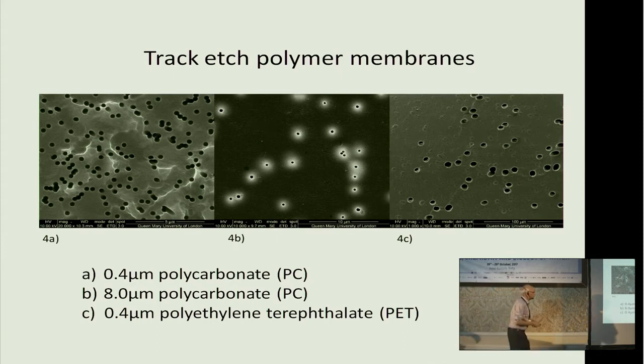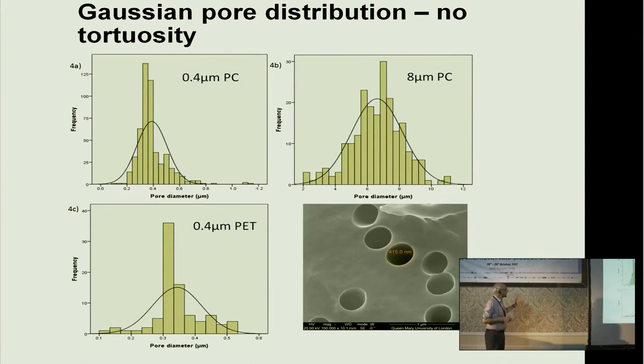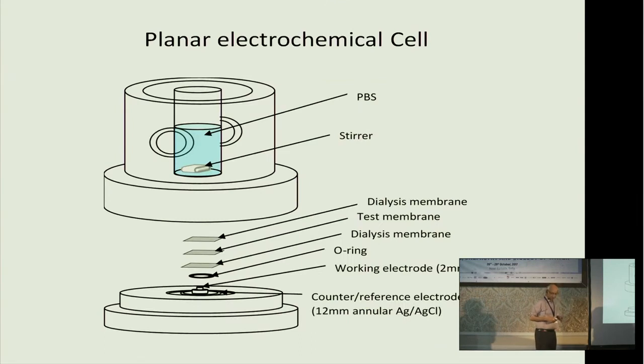So these are the membranes that we worked with, and it's the sole reason I'm here talking to you, because of the membrane science. They are beautifully, elegantly organized in terms of a quasi-Gaussian distribution. But the important thing is that with the right imaging technique, you know absolutely the overall pore area of the membrane. If you know the pore area of the membrane, then you know what to expect in terms of diffusion coefficients, because it's like bulk water diffusion, except through a finite pore area. And these are micron-sized pores. So you expect bulk equivalent transport. Right. This is where we ran into a serious problem.